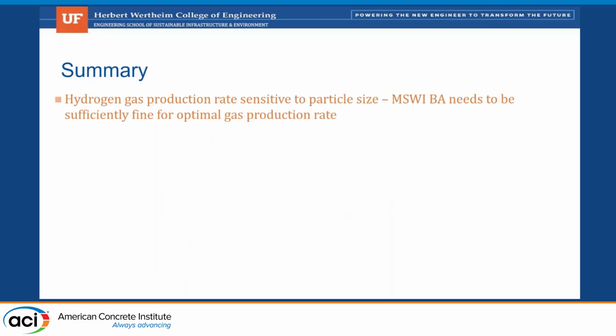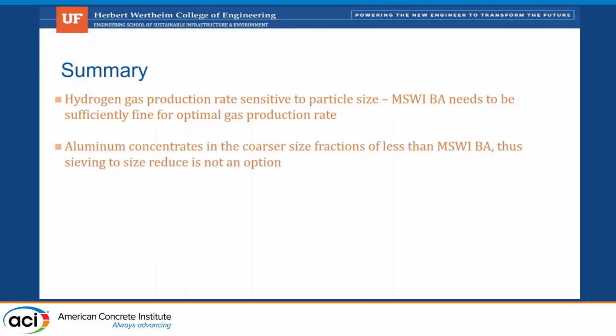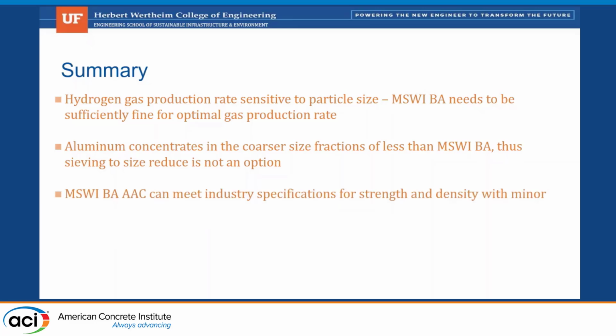With the summary, the hydrogen gas rate is obviously sensitive to particle size. That's a very important part of controlling all this. Aluminum concentrates in the four coarser size fractions. We can meet industry specs for air dry density, and the strength ratio is there.